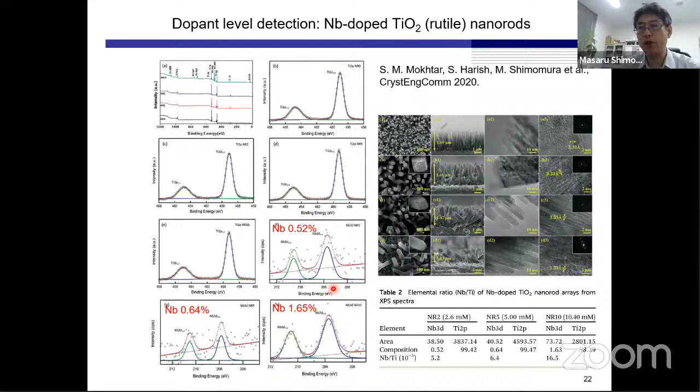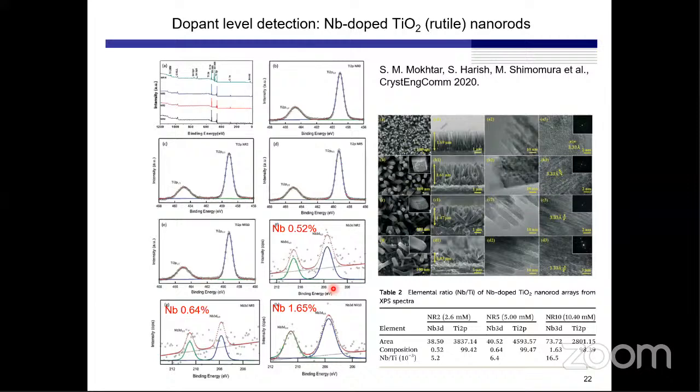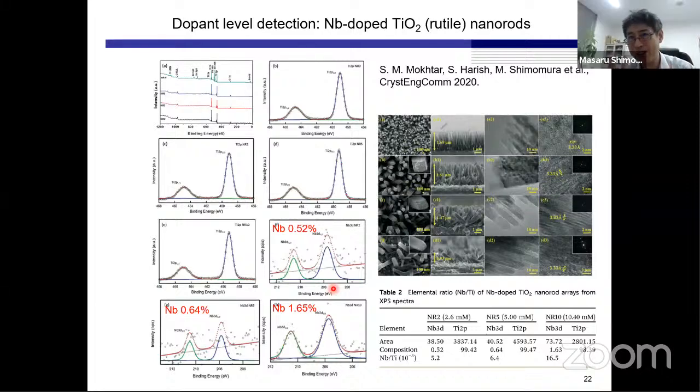If you can estimate the size of the domain, okay. Is it micron scale or nanoscale, uniformly mixed? If it is uniformly mixed, then by using core-level chemical shift maybe we can determine it. But with just a difference of crystal phase, the elemental composition is the same. Is it correct? The elemental ratio is the same. So if so, XPS is not suitable for determining the phase.